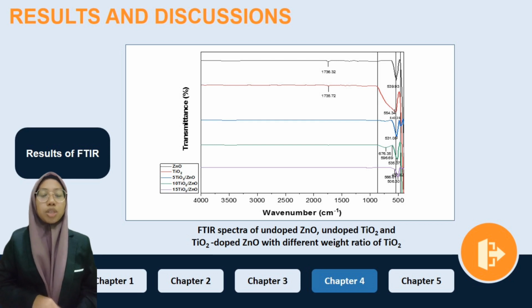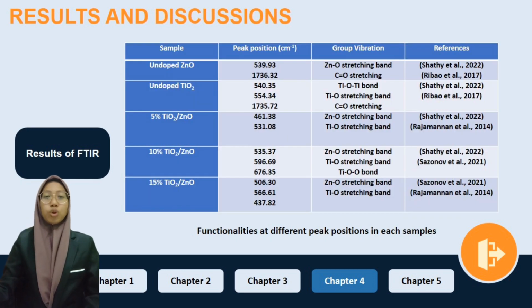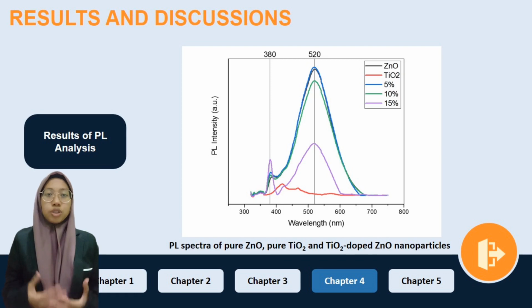The strong absorption peaks obtained between 430 and 540 are attributed to the stretching mode of Zn-O. The peak observed at 676.35 may be associated with the vibration of Ti-O. The other peaks at 1735.72 and 1736.32 may correspond to the carboxylate, which is C=O stretching. For more detail, we can refer to this table, where it shows the functional group for each peak from this FTIR spectra. This graph shows the photoluminescence spectra of titanium dioxide doped zinc oxide nanoparticles.